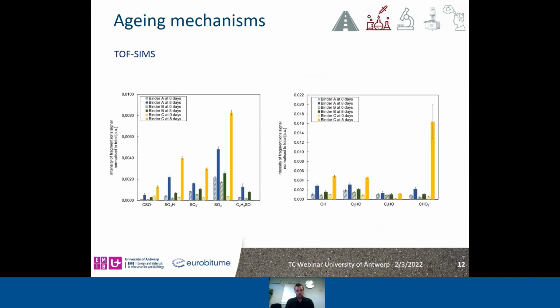Here we will focus on oxygenated products, which all were increased after the completion of the fast rate phase, independent of the binder used. And this supports to some extent the FTIR data, since all the sulfoxide-containing fragments on the left and all the oxygen-containing fragments on the right were increasing upon aging, and especially after the completion of the fast rate phase.